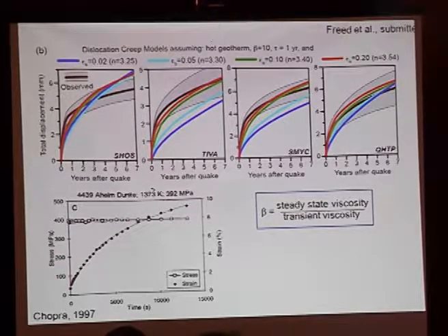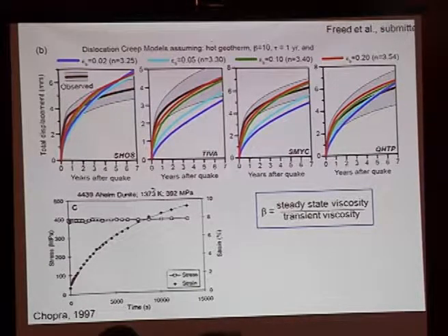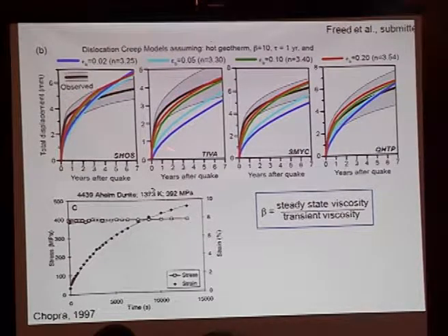This is representative of a transient creep response that maybe some of you have heard of, and Burgers models and things like that explain it. If you account for this transient type of creep response, and you can see right when you start the high load, you get a very, very high strain rate, which might give you a viscosity 5 to 10 times smaller than the steady state viscosity. After you account for that, these curves actually kind of nail not only the total displacement and the azimuth of the displacement, but also the time history, or the evolution in the strain rate.